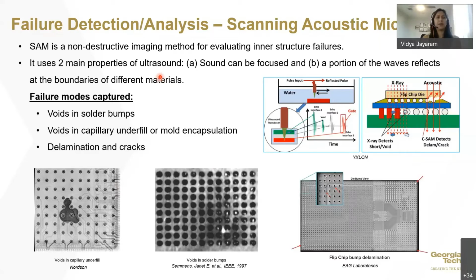So the main failure modes captured here again would be the voids in solder bumps, voids in capillary underfill, or mold encapsulation, like you see in this image here. And it's also very useful in detecting delamination and cracks. So this is another great non-destructive technique to capture a lot of these failure modes.